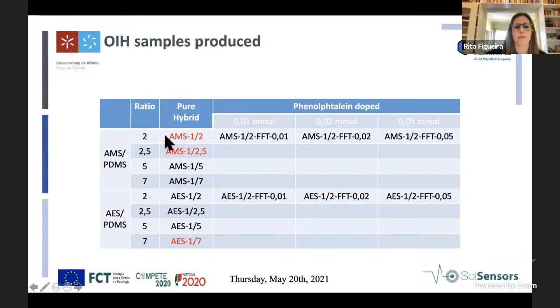So we produced samples with a ratio of aminopropyl silane to PDMS of 2, 2.5, 5 and 7. The higher ratios did not give good results, so I'm not going to discuss them here. And the lower ratios we used with different contents of phenolphthalein. We prepared them with aminopropyl silane and with aminoethoxysilane.